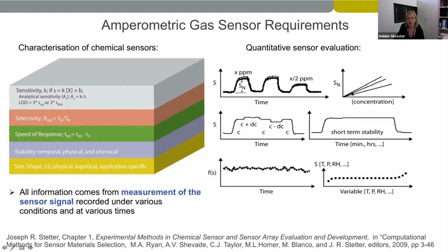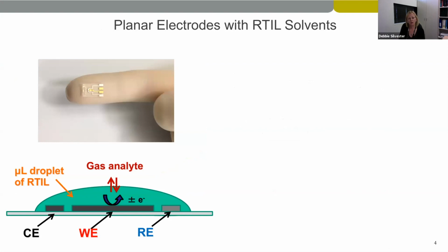And once you have a linear calibration graph, then this sensor can be further tested for its short-term stability. So this is where you apply a potential for a longer time, and ideally it will have a good short-term stability in that it will maintain a constant current over a short term. And then finally, once the sensor device has passed these tests, then it goes on for further tests to look at the effect of changing the temperature, the pressure, and the relative humidities. So the gas sensor manufacturers do a lot of testing of their devices.